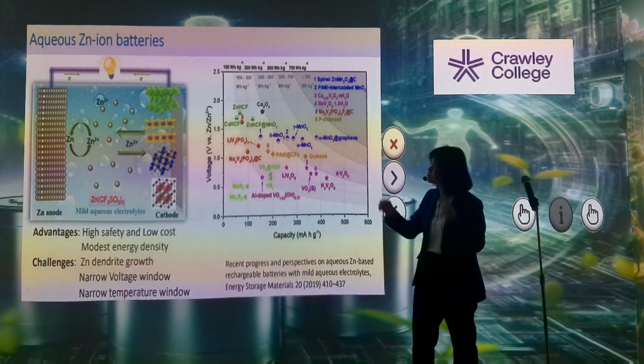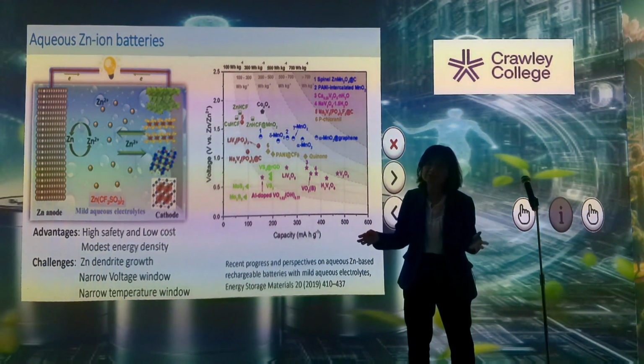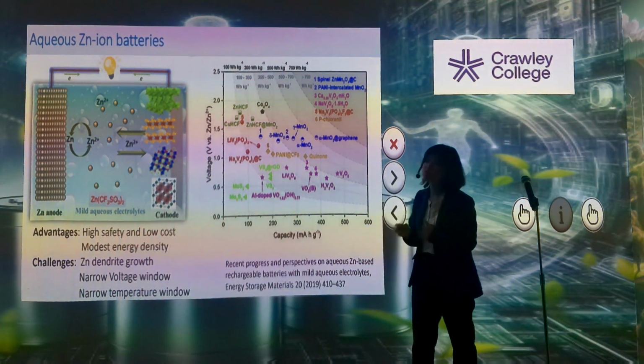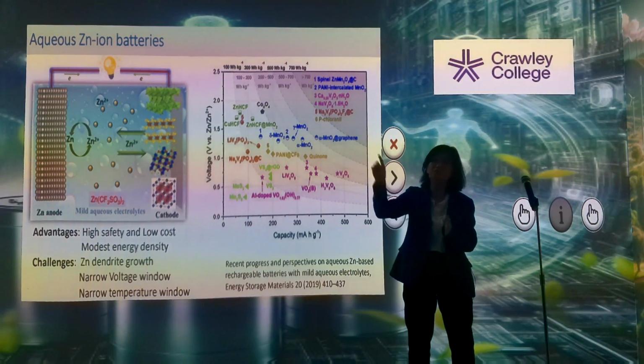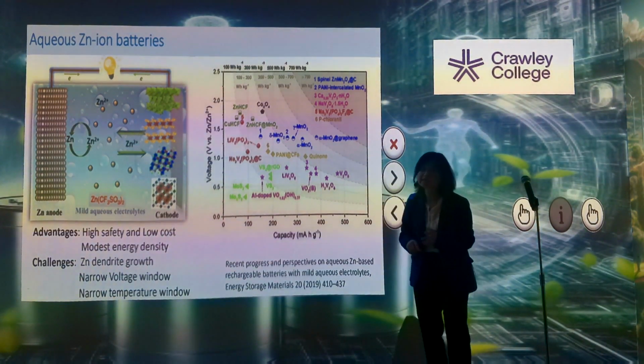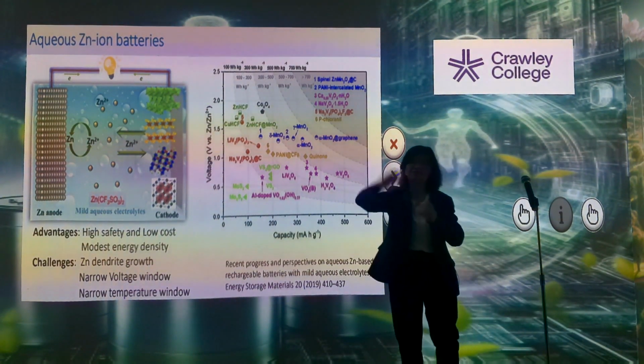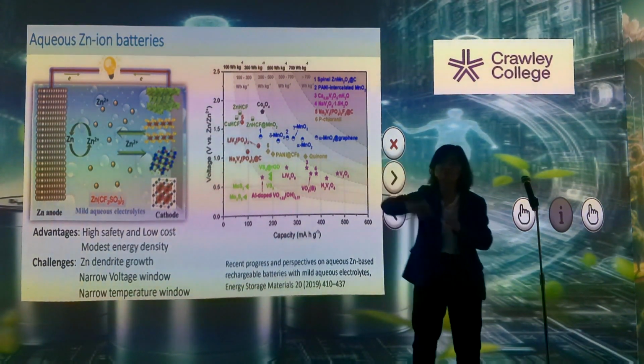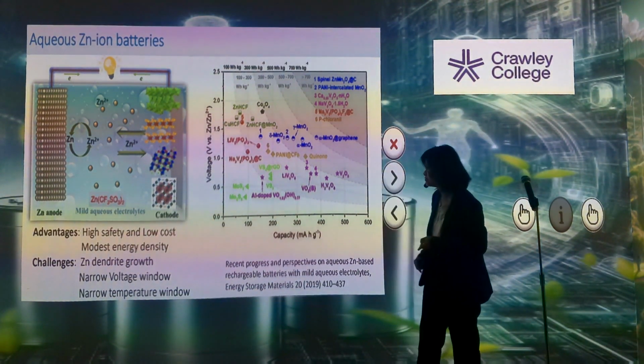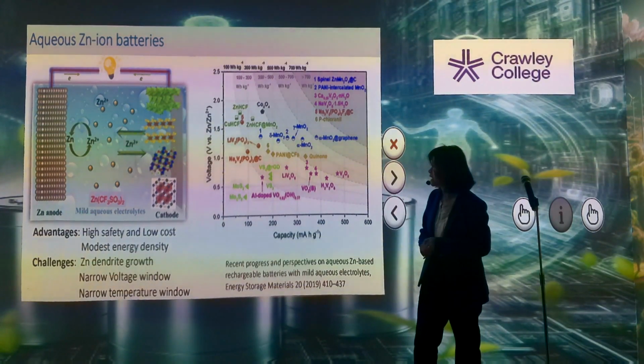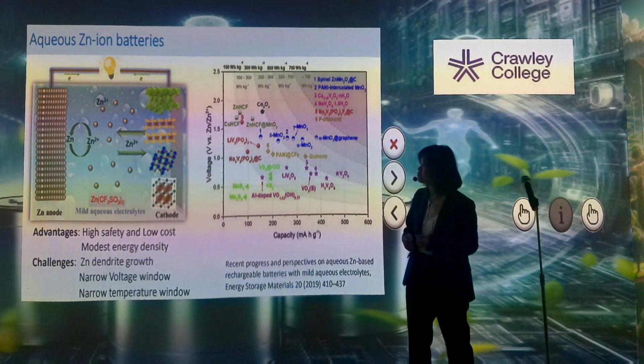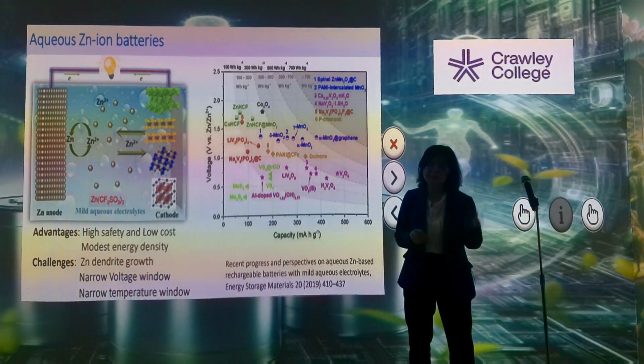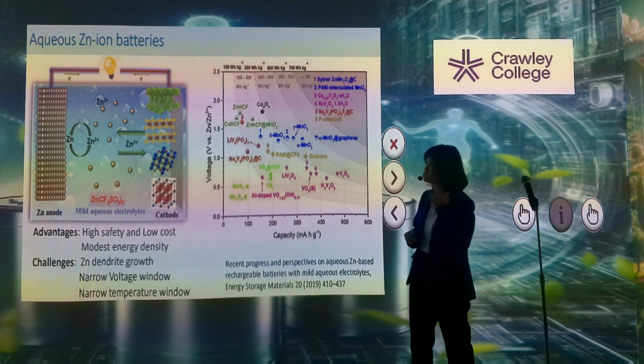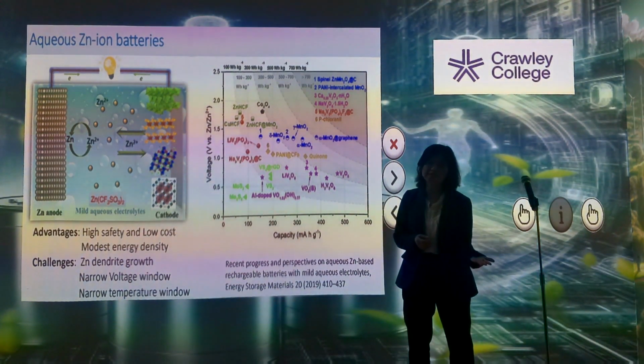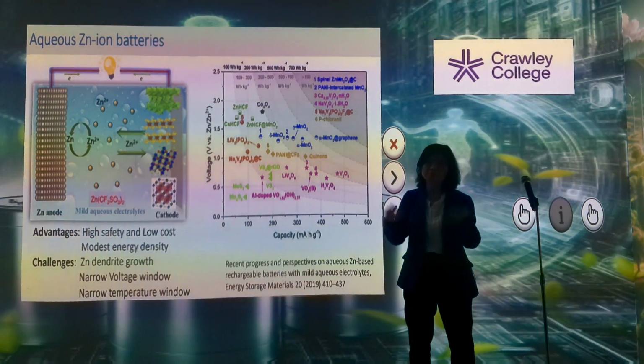And because you use water-based electrolyte, you have a narrow voltage window, because once you reach voltage 1.23, you will have electrolysis of water reaction happening. You generate hydrogen and oxygen. You don't want that. And also because of its aqueous electrolyte, the temperature is a problem. If you want to go to below 0 degrees C, water becomes solid.